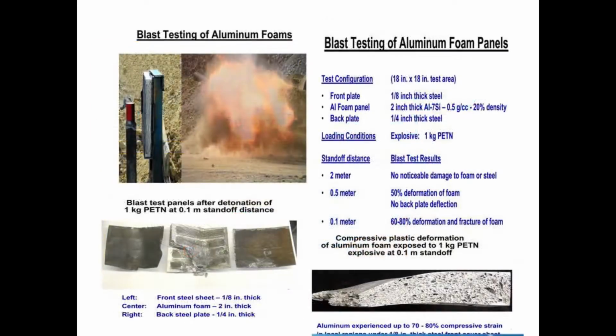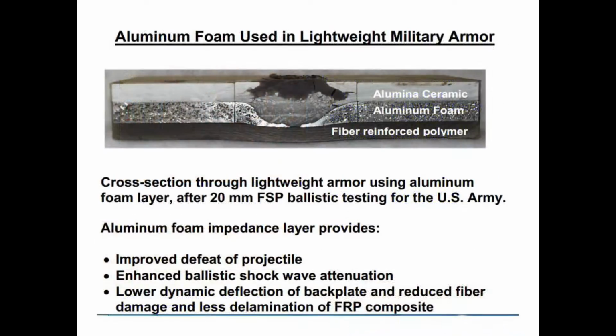And these are some images I have taken from the net. These are the tests they have done for blast resistance. This is the multi-layer armor where the aluminum foam is kept at the core, and at the top they have kept ceramic armor materials, dense alumina ceramics or zirconia ceramics can be used, and at the bottom they use fiber reinforced polymer. In this way, multi-layer armor has a better capability to resist ballistics of higher caliber. And they are using this even in the tank.